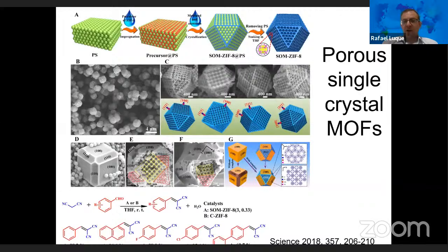And our model reaction, which is in fact a very simple Knoevenagel type of chemistry at room temperature, showed, however, that this extraordinary contribution of macro and microporosity together with the single crystallinity was found to achieve excellent yields in this particular reaction that was selected as a model reaction, as compared to conventionally synthesized MOFs that you see at the bottom, in these bars, under conventional hydrothermal conditions. Again, stressing the potential of developing this unique porosity in the materials as well as the single crystallinity. A follow-up paper of this is currently submitted on a biomass-derived application of the materials.